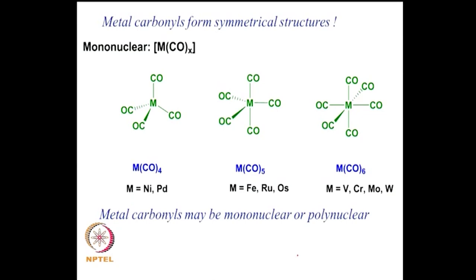I mentioned earlier that metal carbonyls tend to form reasonably symmetric structures. They are not necessarily tetrahedral or octahedral, although these tetrahedral and octahedral complexes are indeed observed. Typical examples are nickel tetracarbonyl, which is probably the one that chemists encounter first, because that is very easy to synthesize, and chromium hexacarbonyl. So, that is another molecule, and that has got a nice octahedral geometry. But you will notice that the complexes all have carbon monoxide symmetrically distributed around the metal. This seems to be a hallmark of the type of compounds that are formed by metal carbonyls.